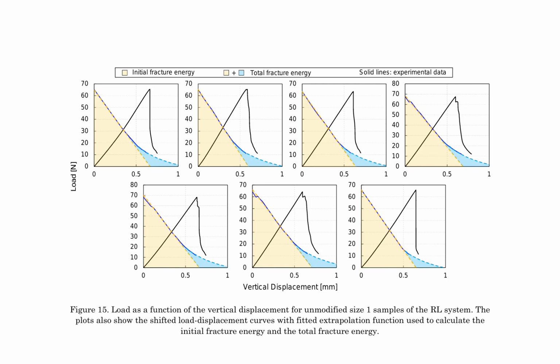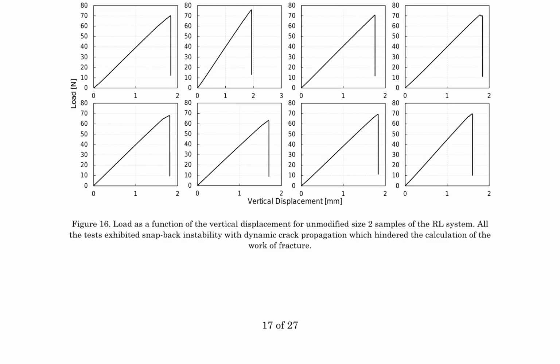The plots show the shifted load displacement curves with fitted extrapolation functions used to calculate the initial fracture energy and the total fracture energy. The RL system exhibited snapback instability with dynamic crack propagation, which hindered the calculation of the work of fracture for size 2 samples.